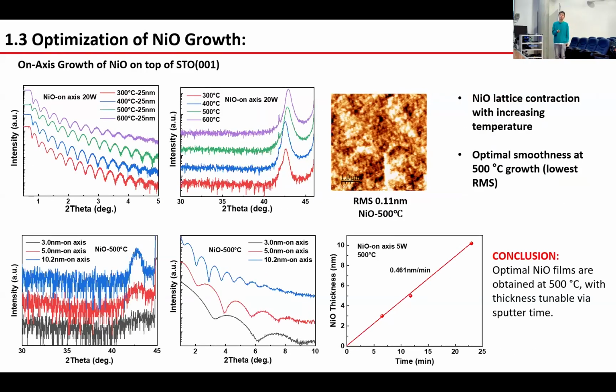Then I optimize the nickel oxide growth. First, I grow an identical thickness of around 25 nanometers, changing the temperature from 300 degrees to 600 degrees, and with increasing temperature, the nickel oxide peak shifts to a higher angle, indicating lattice shrinkage with lower oxygen vacancies, and also the lowest surface roughness is attained at 500 degrees. So we could achieve the optimal smooth growth at 500 degrees.